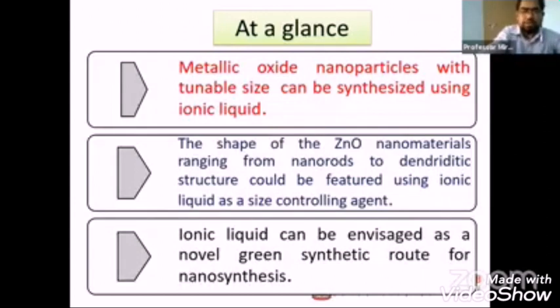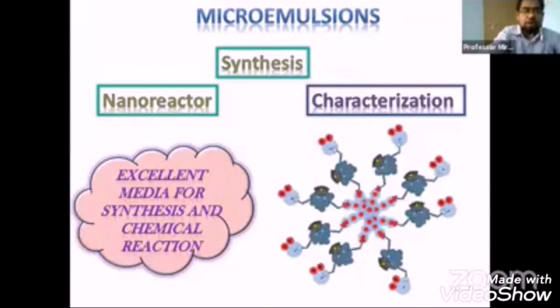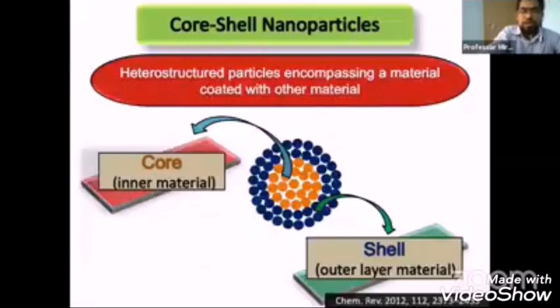And the shape of the zinc oxide nanomaterials, ranging from nanorod to dendritic structure, could be featured using ionic liquid as a size controlling agent. So ionic liquid can be envisaged as a novel green synthetic route for the nanosynthesis. Another one is a microemulsion, which we use basically as a nanoreactor. It is an excellent medium for synthesis and chemical reaction. So actually we use this material at first for single silver nanoparticles preparation and other zinc oxide preparation.